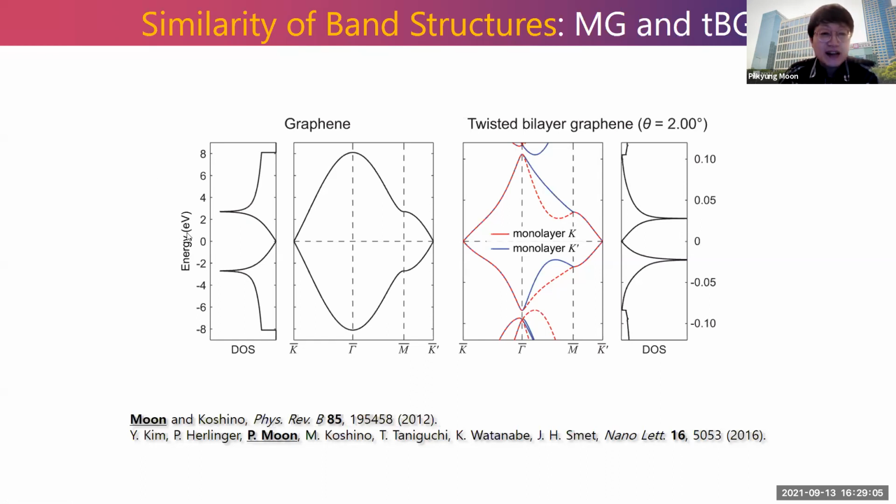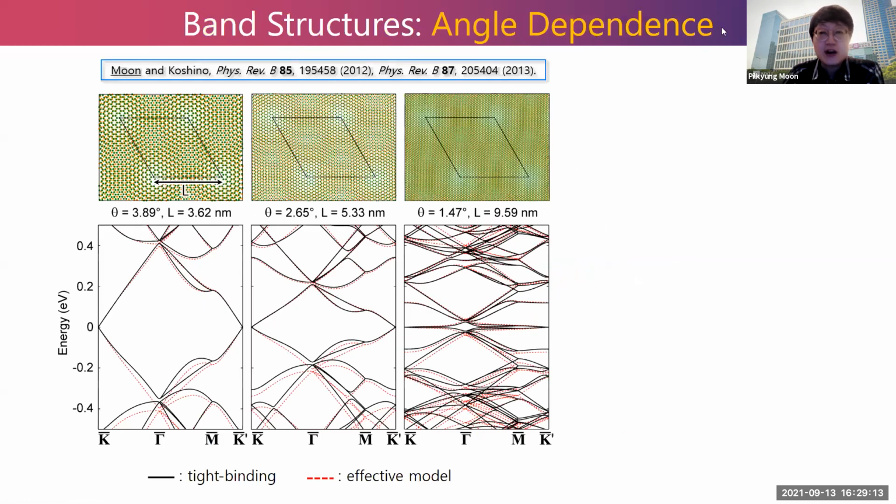Here I plot the band structure of twisted Moiré graphene with three different rotation angles. The slope corresponds to the Fermi velocity of twisted Moiré graphene. As the rotation angle decreases, the Fermi velocity gradually decreases and even drops to 0 at a specific angle. This is a very interesting point.